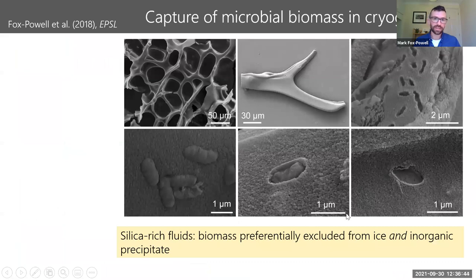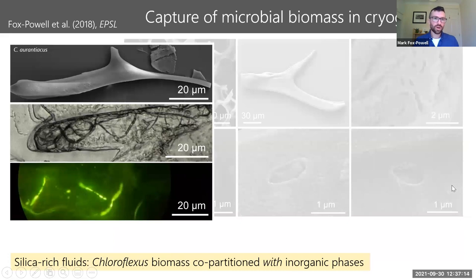And what we found is that in most of the cases of our biological biomass, these cells were preferentially excluded from both the ice and from the silica, and they accumulate here at the edge, the surface of this silica particle. So the silica here has been removed from ice, in this case just by melting the ice and drying it. And we can see these cells have been sandwiched between the advancing ice face and the precipitating amorphous opaline mass. But that is not the whole story.